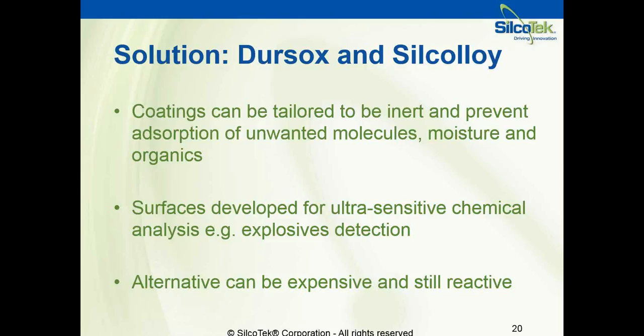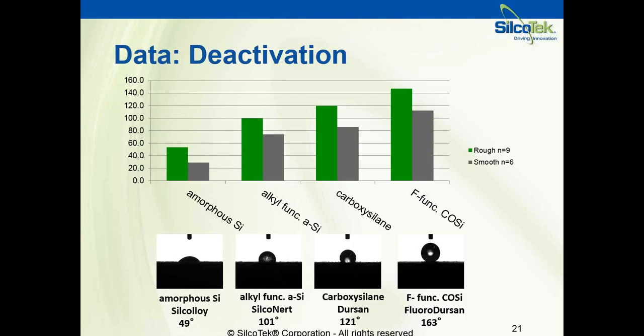So this obviously has implications that are important when you're talking about a chamber or other process components in a semiconductor device manufacturing application. Moisture is extremely important and can be extremely detrimental to any process, such as the ones that I've just mentioned. So you can see in this graph that on the left is our Silcoloy coating, which is, again, simply a layer of amorphous silicon. If anything, this is a hydrophilic surface with only a 49-degree contact angle.